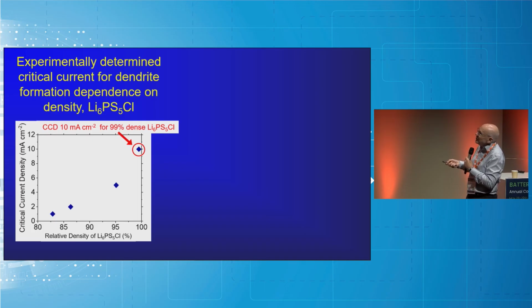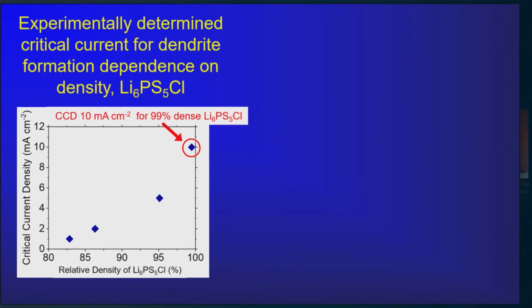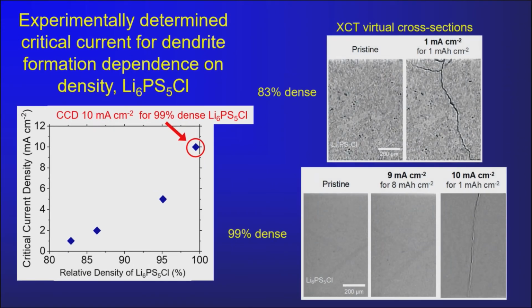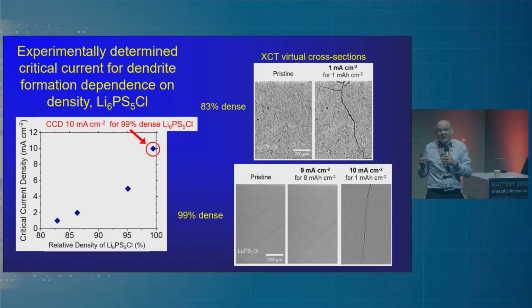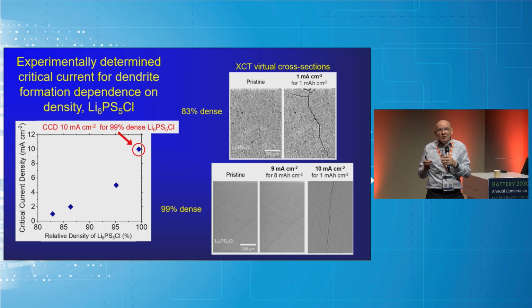Normal argyrodite pellets are about 83% dense, that most people use. We've densified to 99%, and we've got a critical current of 10 milliamps per square centimeter. If you just look at these XCT images, this is plating 8 milliamp hours of lithium. That's about 40 microns of lithium, so no tricks here of tiny amounts of lithium. At 9 milliamps, a high current density, and no dendrites. So in the case of argyrodite, you can indeed achieve this improvement in CCD by controlling the microstructure by densification.